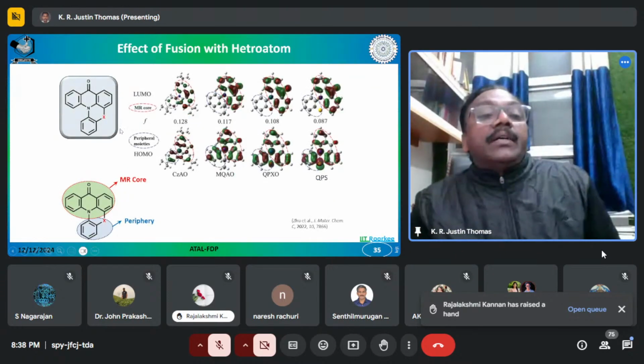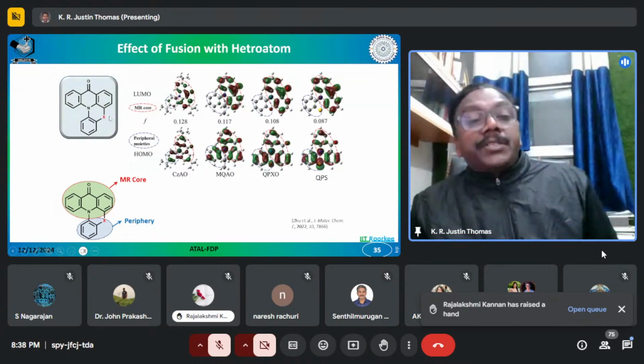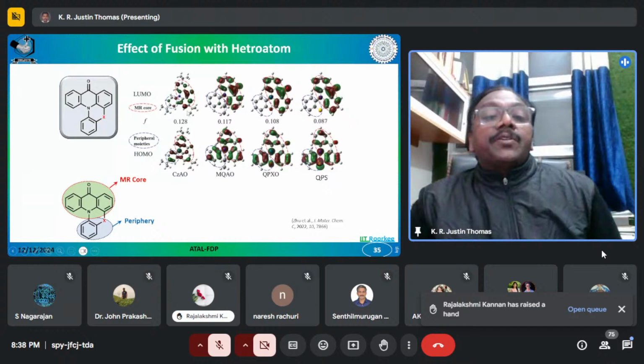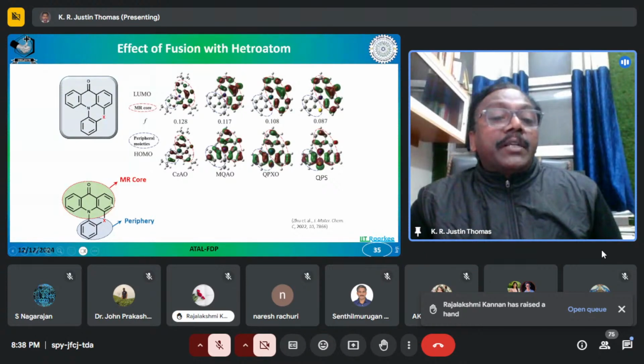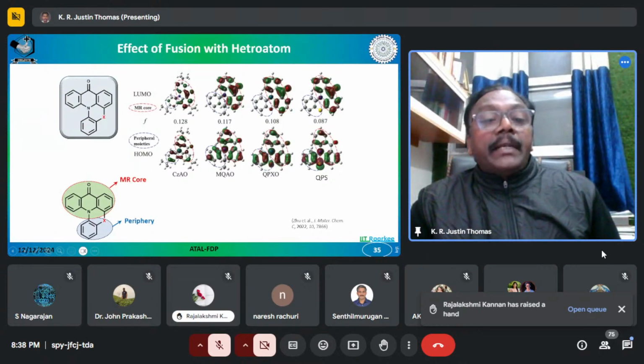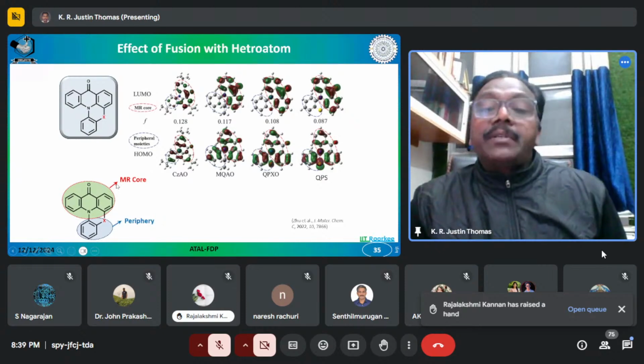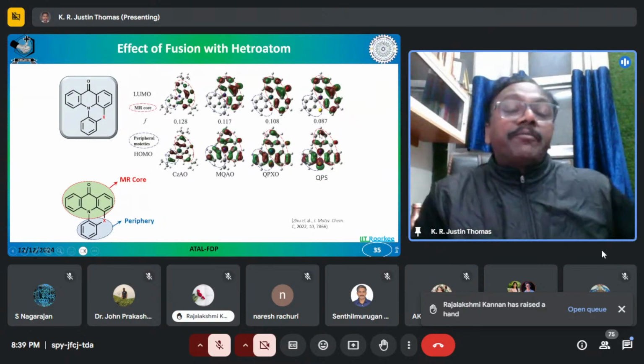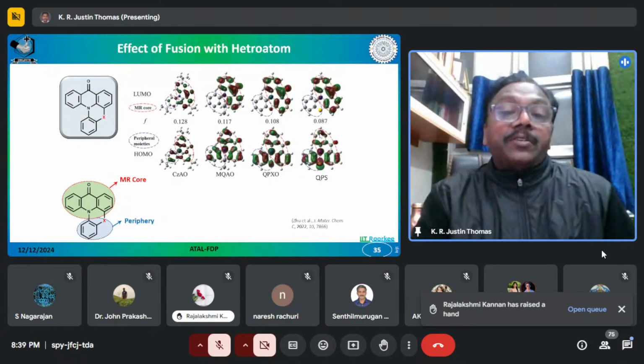You can see here, when you change the X electron rich, you will have long range charge transfer dominating. So if you look here, when X is equal to oxygen, this is oxygen, and this is sulfur. This is selenium and so on. So what you see here is when you increase the electron richness of X, the peripheral part contributes more to the HOMO. That means the short range charge transfer within the MR core is still there, but additionally the peripheral donor also contributes to the charge transfer. That is the long range charge transfer. So that is dominating here. Okay, so this is the fundamental electronic aspect about these molecules.